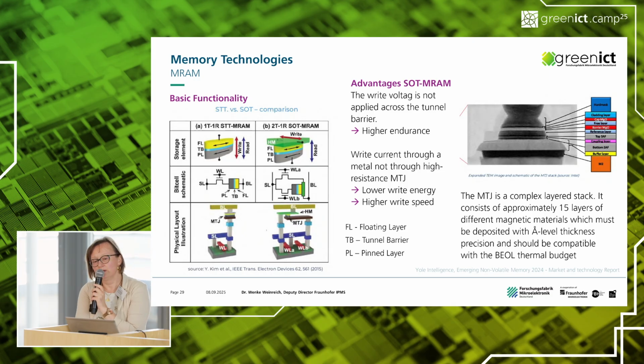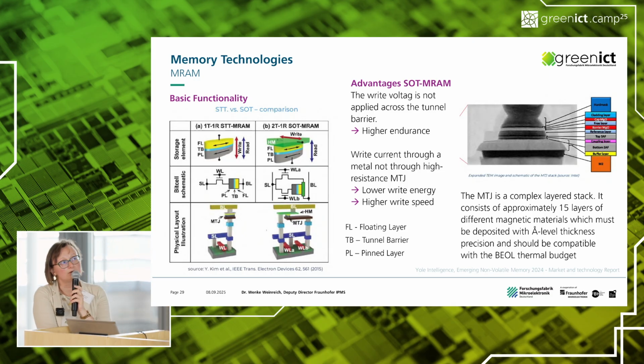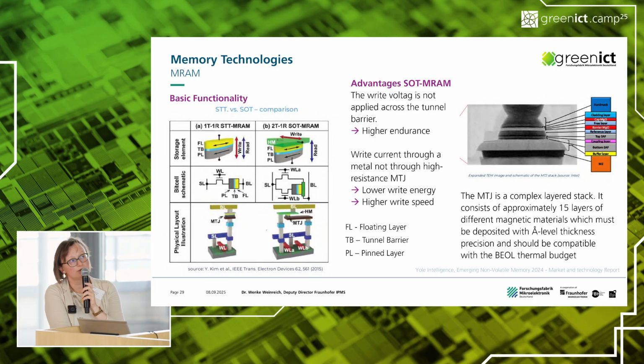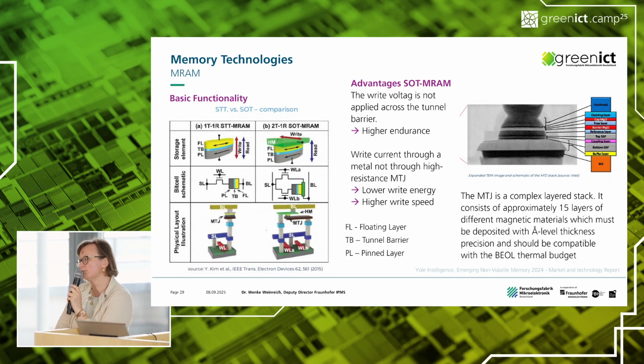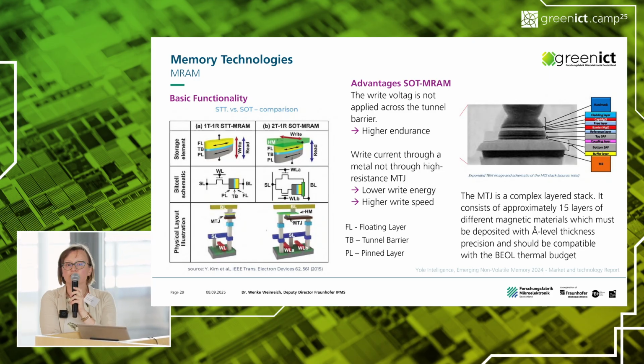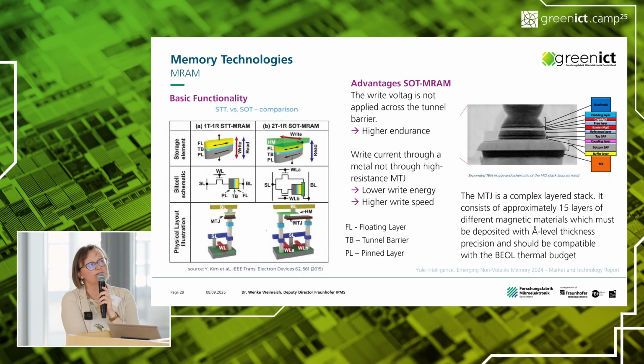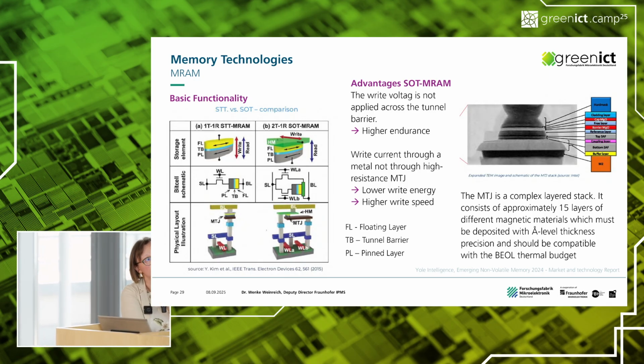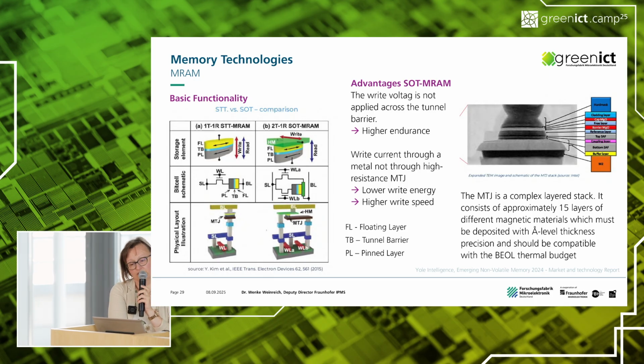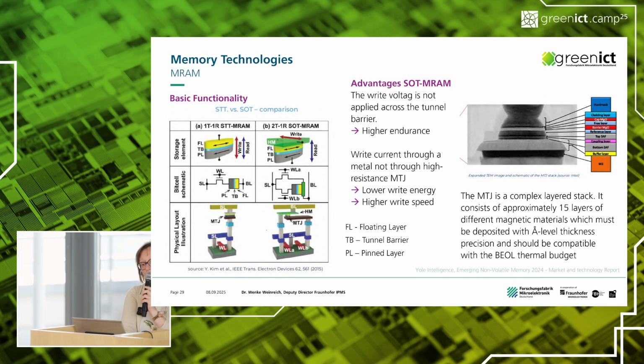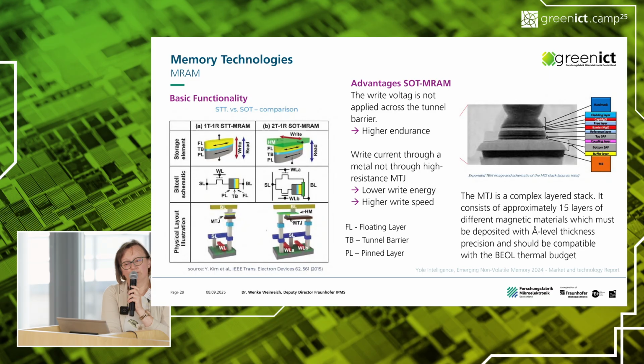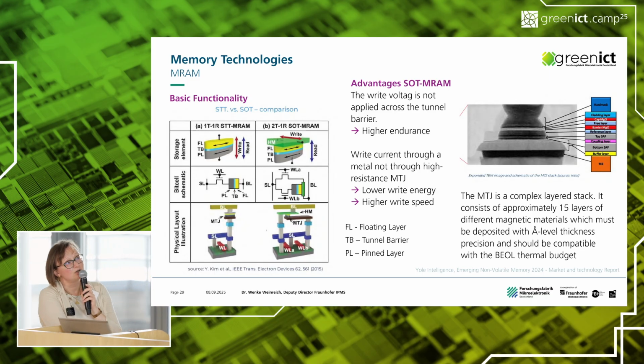What does that mean? If you want to embed the material on top of a CMOS, you are not allowed to harm the CMOS below. That means you can only fabricate at lower temperatures. And that sometimes is not good if you want to have a really well-defined and optimum material stack. So that is here the real challenge. But it's working, so a lot of good engineers find good solutions for this kind of memory, and it works quite well. And that's why you will find it as a TSMC technology.